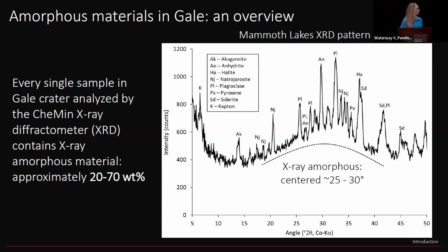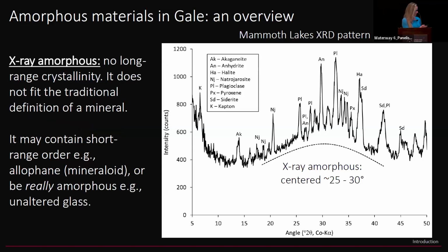And this is what it looks like for folks who do XRD. The amorphous component shows up as this amorphous hump, background hump, and it's usually between 25 and 30 degrees 2 theta. And when I say amorphous, I mean that it does not contain long-range crystallinity. So this is like a really basic Geo 101 definition. It does not fit the traditional definition of a mineral.